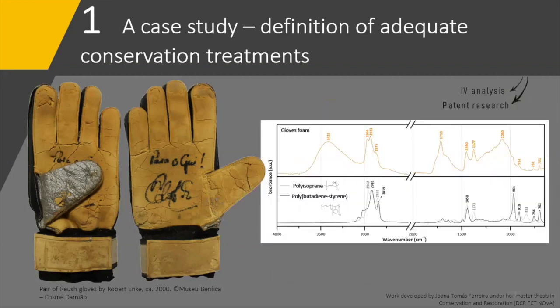However, by crossing the information obtained by infrared analysis and the patent research on sports equipment, we surprisingly characterized the foam as a synthetic latex-based polymer made of polyisoprene, polybutadiene, and polystyrene, thus requiring the selection of different consolidants. So in sum, infrared spectroscopy allowed us to target the treatment to the polymers identified in the gloves and thus to make a more informed and appropriate study for this challenging case.